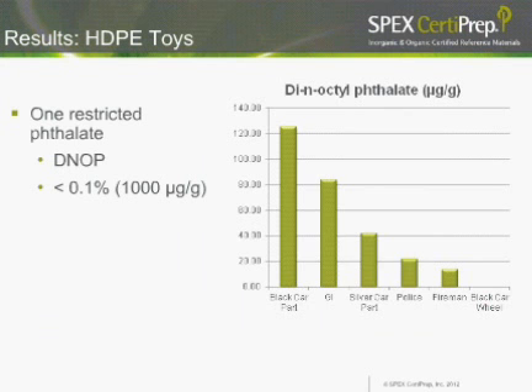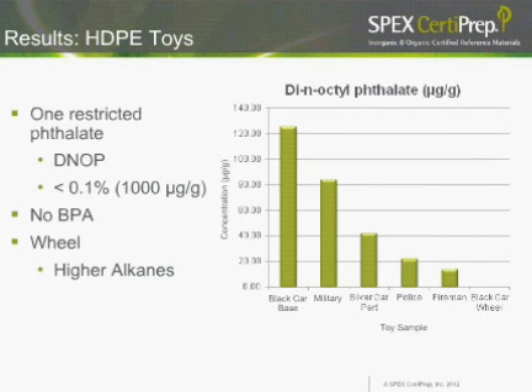In our toy cars, we found that there was only one restricted phthalate in the toy car parts. This was the DNOP. And the level we found this DNOP at was way below the 0.1%, or the 1,000 microgram per gram level, that was allowable by the method. We were able to discern that there was no measurable BPA, which we didn't expect, to be honest. One of the strange things, or not so strange things, that we found, but we were able to see with our scan mode, is that higher alkanes were being extracted out of the wheel of the toy car.